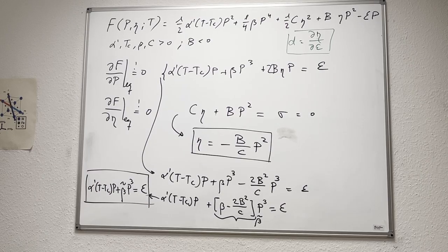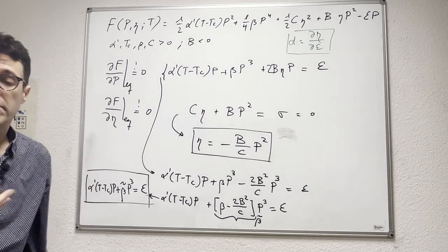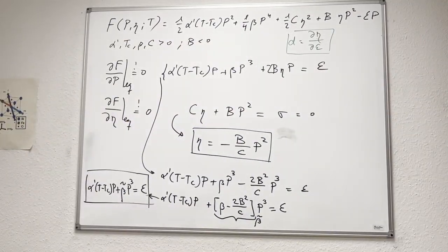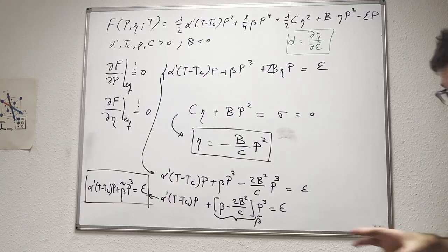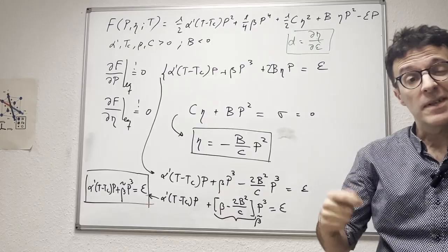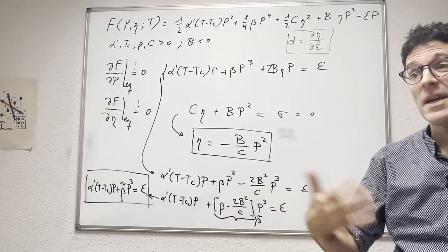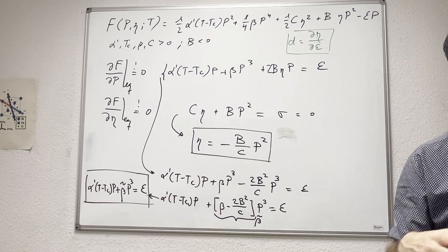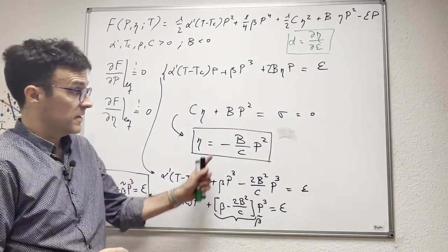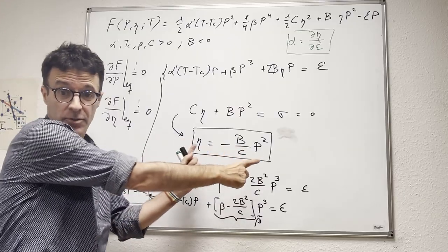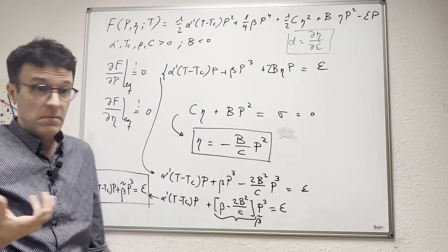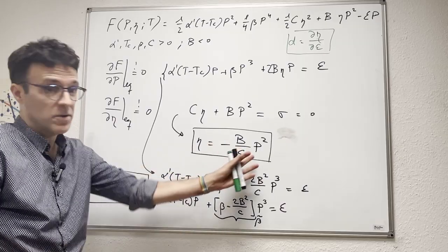Okay, so what have we done here? This can generally be done as long as the energetics is not too complicated. Well, if the energetics is not too complicated, it can even be done analytically, let's say. When we have a secondary variable like the strain here, which is a slave to the polarization, is very important for the physics, but ultimately it will always adopt at equilibrium a value that is dictated by the polarization. When we have such a situation, we can essentially get rid of the variable in our theory by simply expressing it in terms of the primary order parameter.